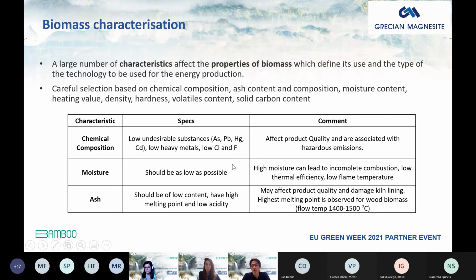Moisture should be as low as possible, because high moisture can lead to incomplete combustion, low thermal efficiency, and low flame temperature. And of course, the ash content should be as low as possible, have a high melting point and low acidity, because, as I said, this may affect product quality and moreover damage the kiln lining. Therefore, the melting point of the ash is very important to us. From all the biomass studied, the highest melting point is observed for the ash of wood biomass, with a flow temperature that can be as high as 1400 to 1500 degrees Celsius.